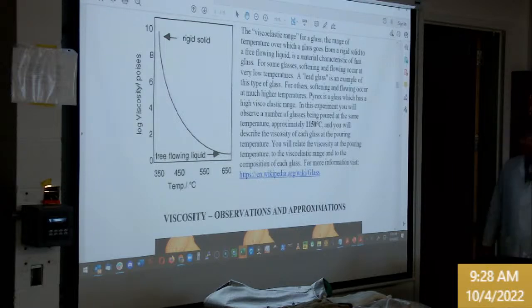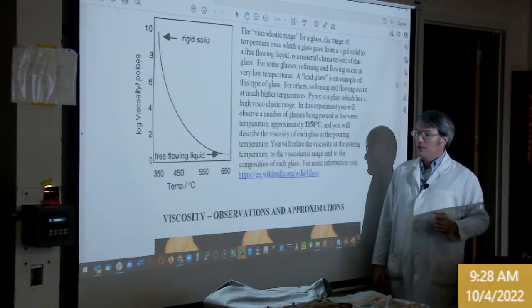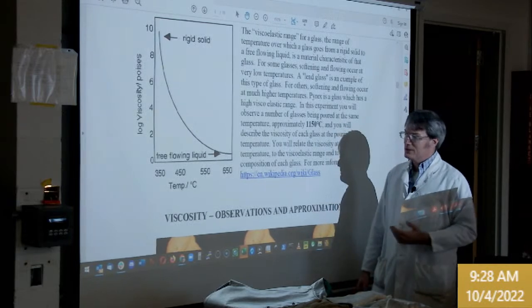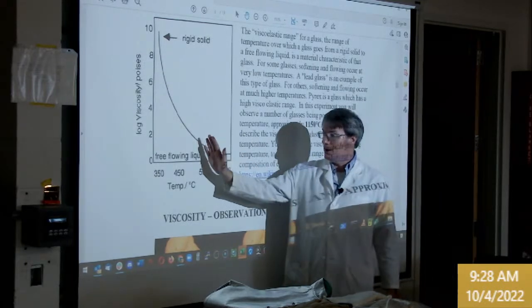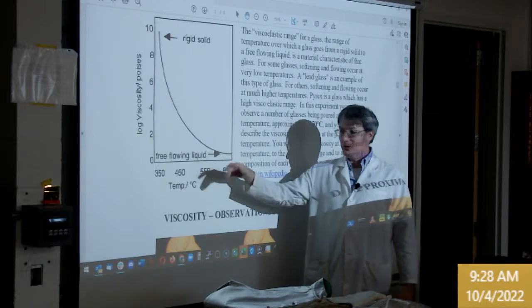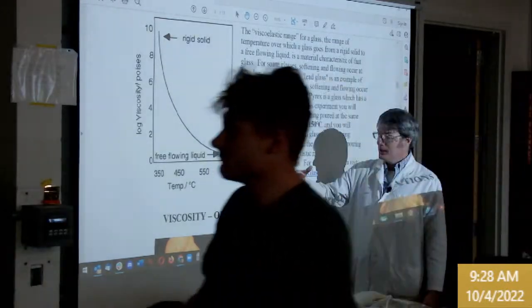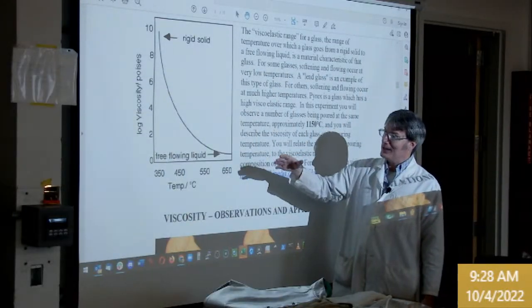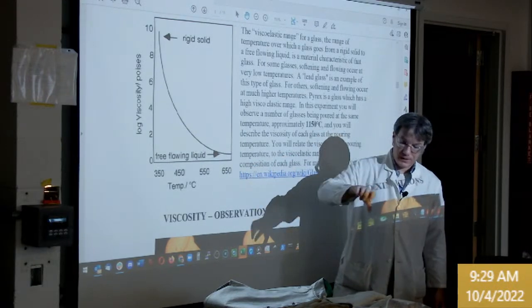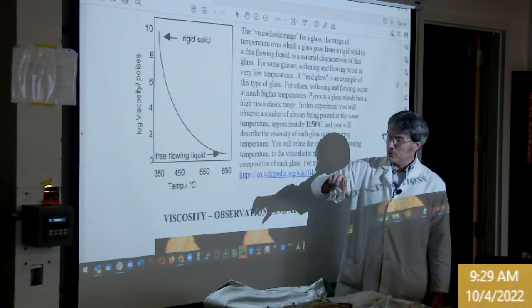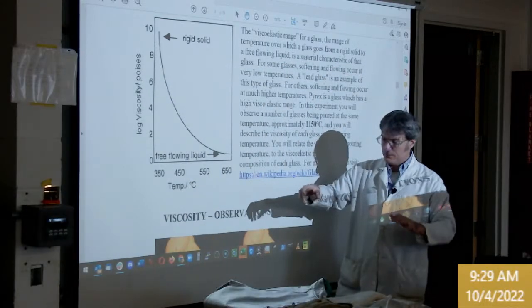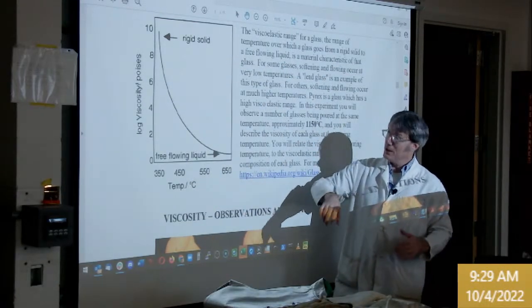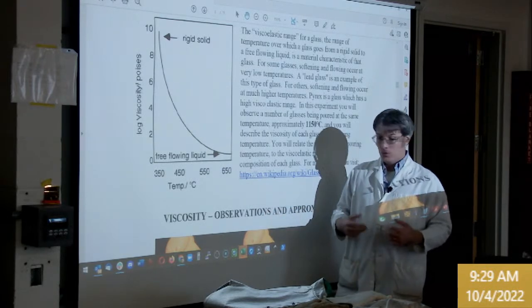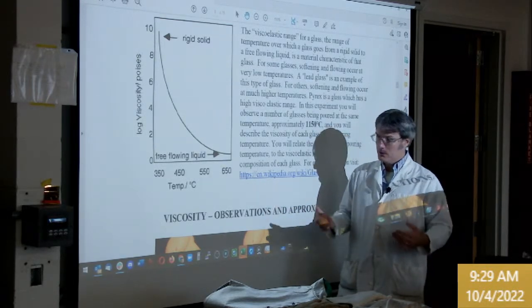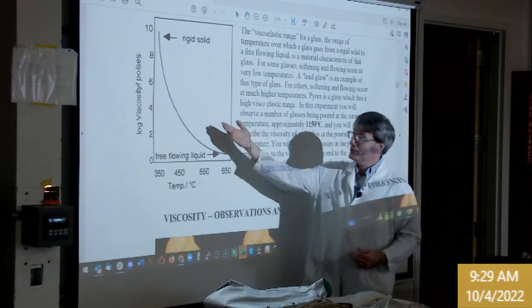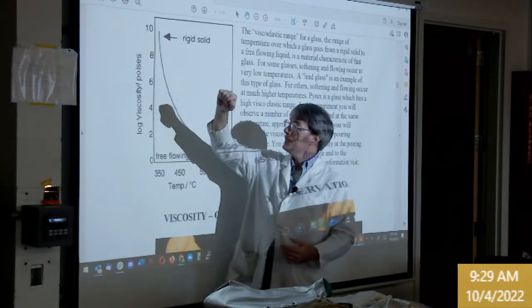We've got this plot here, and this is showing the relationship between viscosity and temperature. Now this would be for a really low melt temp glass, like a highly fluxed lead glass. And so viscosity is thickness of the pour. Low viscosity is like water. It flows very easily. High viscosity, corn syrup, peanut butter, grease, those things are much, much higher.